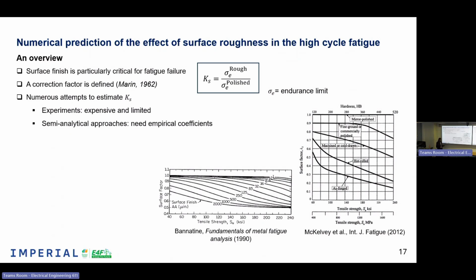That's why they started doing semi-analytical approaches. So the typical waves of surface roughness can be approximated by notches. And these notches have been very well studied by our community. So they try to apply analytical approaches to predict the stress concentration factor, how the stress was growing in the vicinity of the notch. They did it in static, and now to go back to fatigue, what they did is to apply some kind of empirical coefficients. So in the end, we had the same problem because, okay, in static we are good, we have a completely analytical solution, but when we go for fatigue, we need to do experiments to get these empirical coefficients and in the end to get the solution. So it was also very limited.